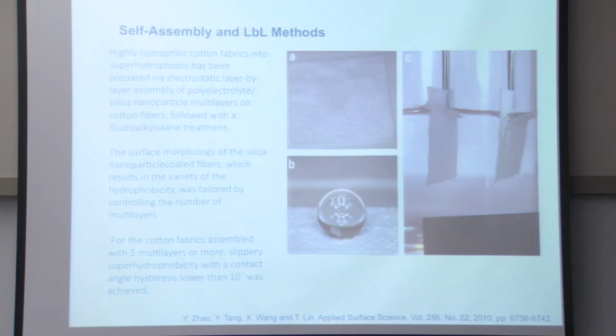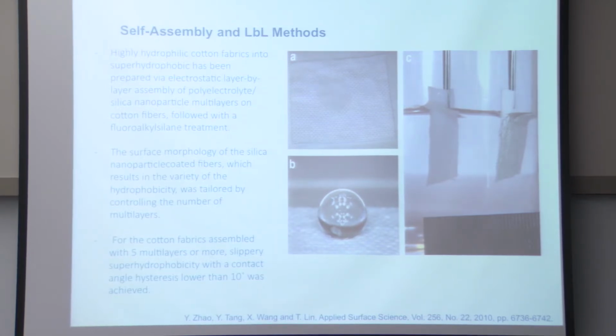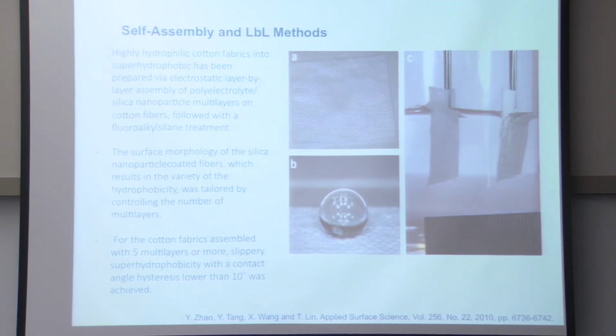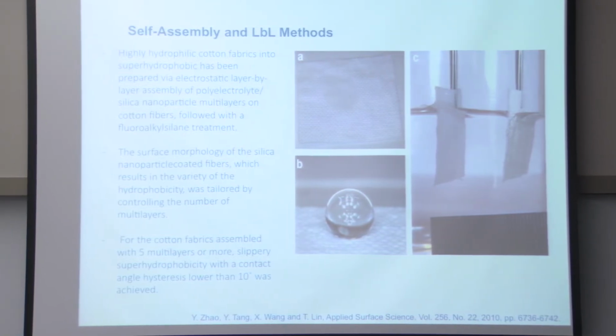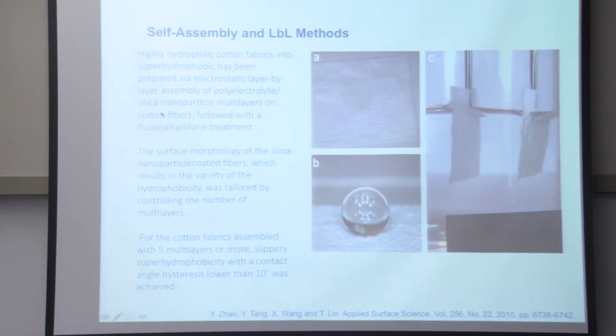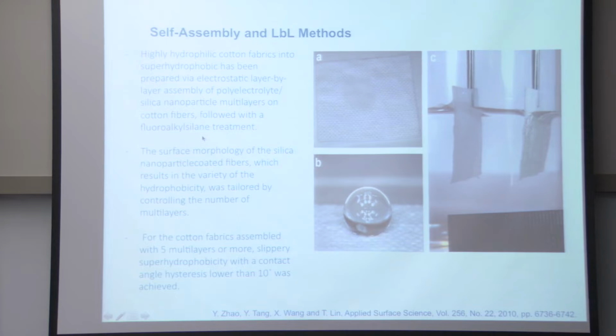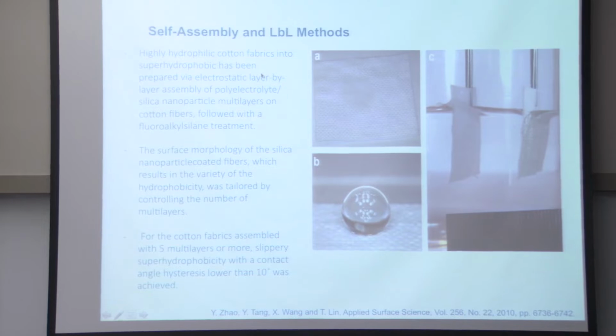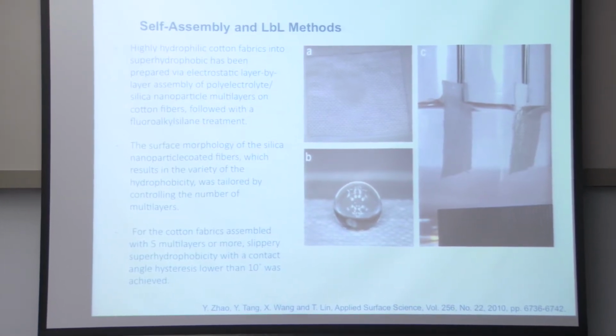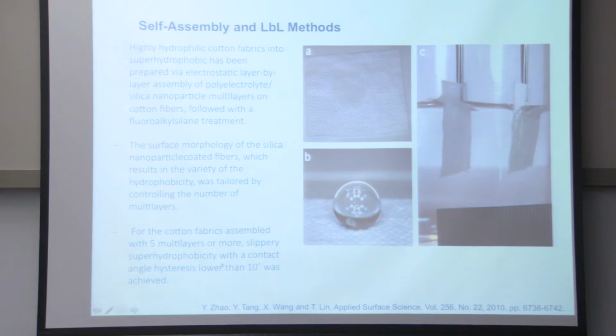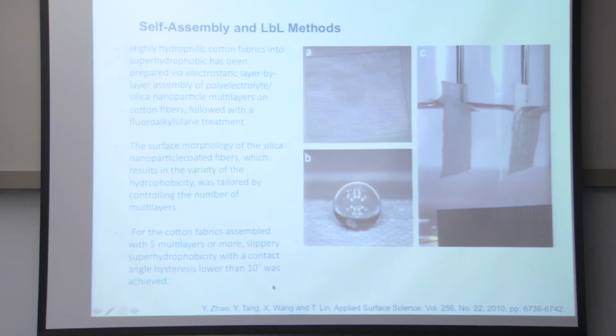Self-assembly and layer-by-layer methods. This has been demonstrated by alternating layers of polyelectrolytes and silica nanoparticles. You can take a cotton fiber or even paper, and after depositing the polyelectrolyte, this was modified with a fluoroalkyl silane treatment. The morphology together with the silica nanoparticle results in multi-layers of particles and polyelectrolytes, enabling it to have a superhydrophobic effect and a hysteresis lower than 10 degrees.